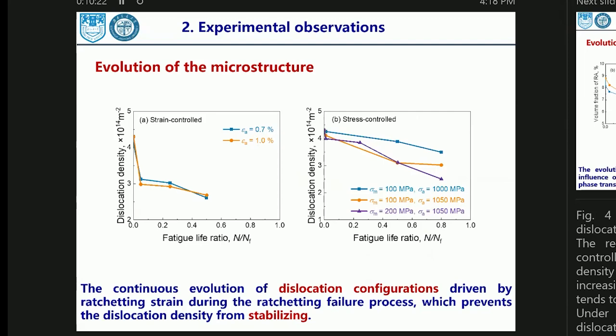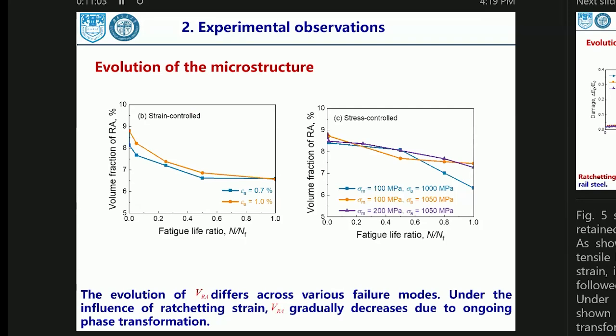And we also find the microstructure evolution during the cyclic loading. This one is strain controlled and this one is stress controlled. We find the dislocation density under the strain controlled mode decreases rapidly in the initial cycles and reaches constant values, but under the stress controlled mode, the dislocation density is reduced slowly and does not reach a plateau. And for the volume fraction of the retained austenite, we also find similar trends. Under the strain controlled mode, the volume fraction decreases rapidly and reaches a constant value, and under the stress controlled mode, the volume fraction of the retained austenite decreases continuously and does not reach a constant value.